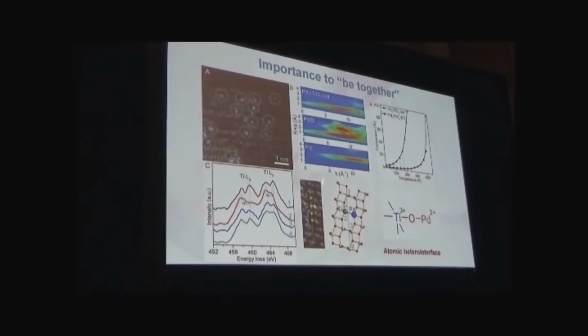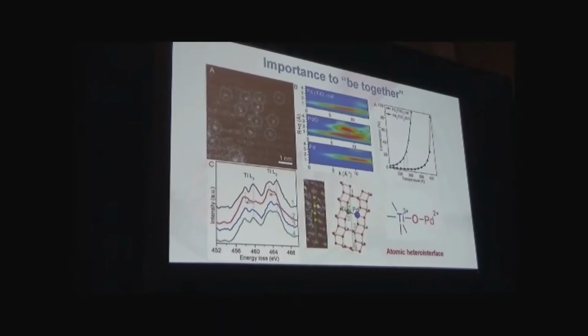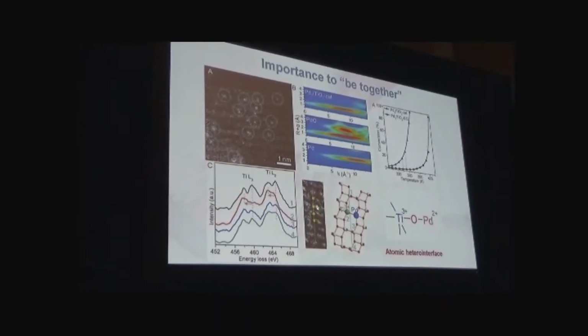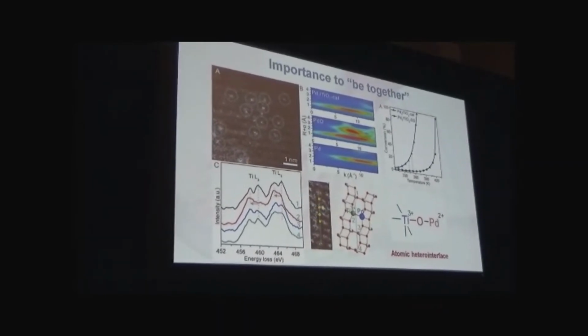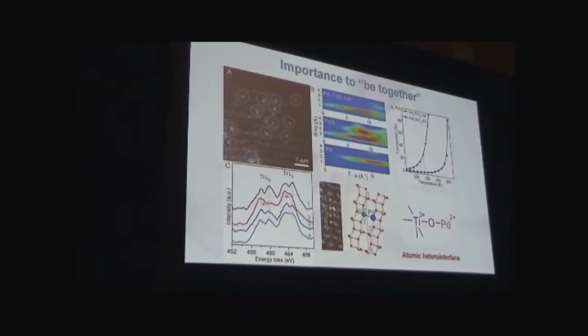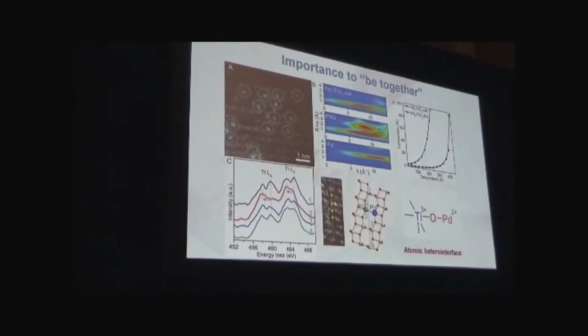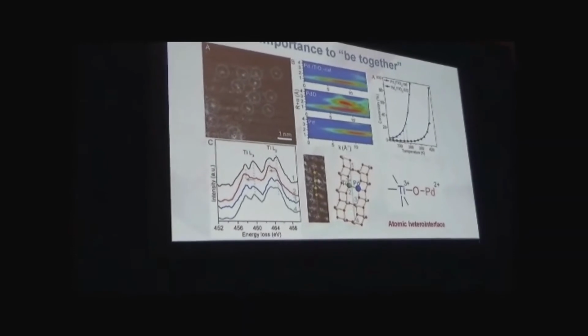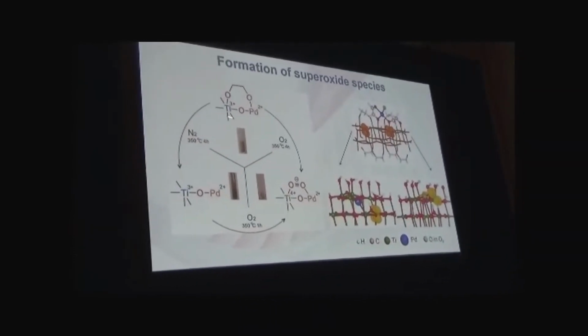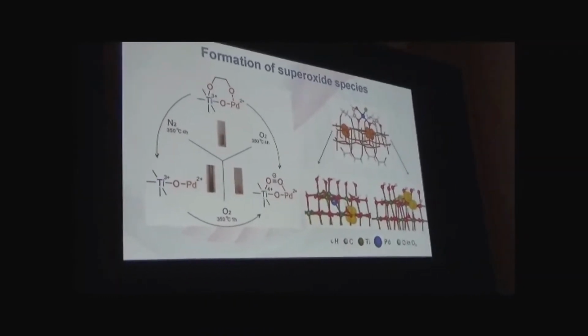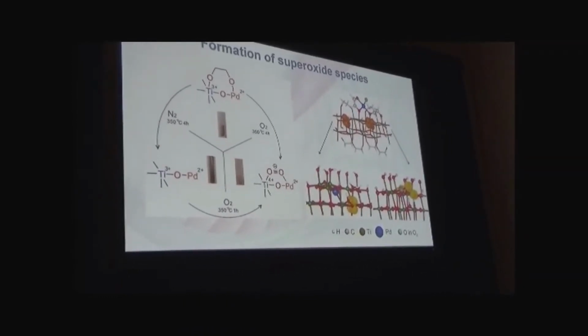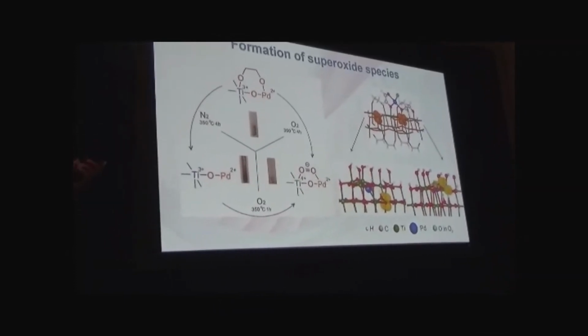Is combined with the TM, HRTM. You can confirm this side is palladium and this side is titanium 3+. So we create some unique atomic hetero interface. Here is the example. We can synthesize the single atom through the photochemical route.